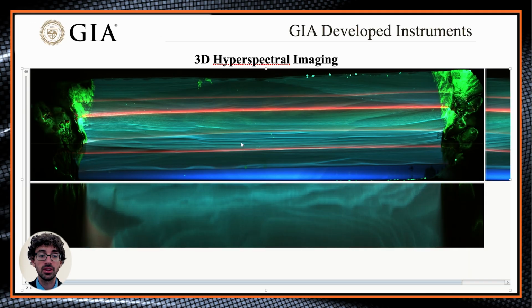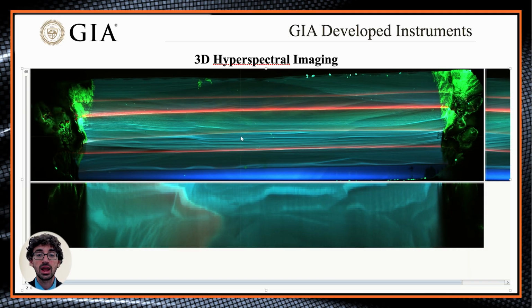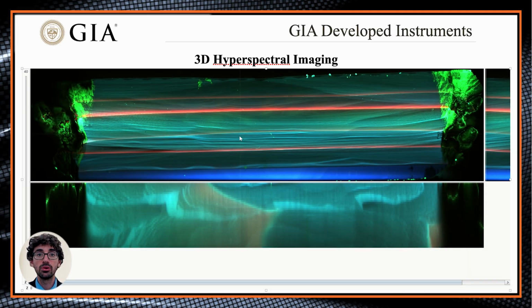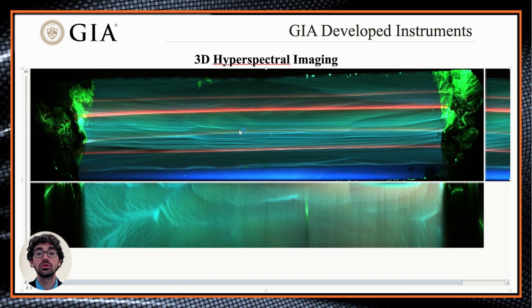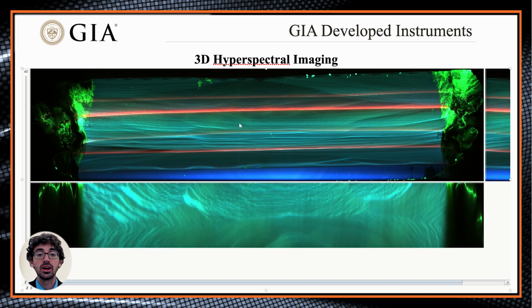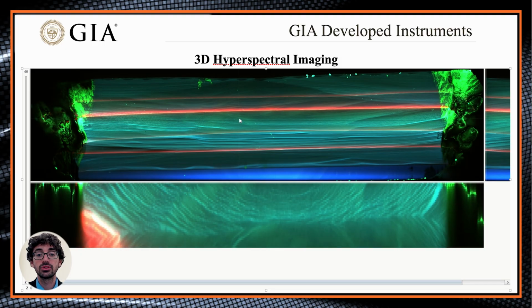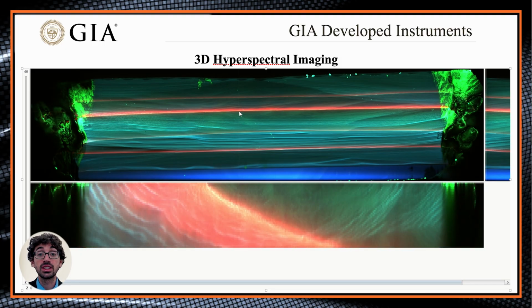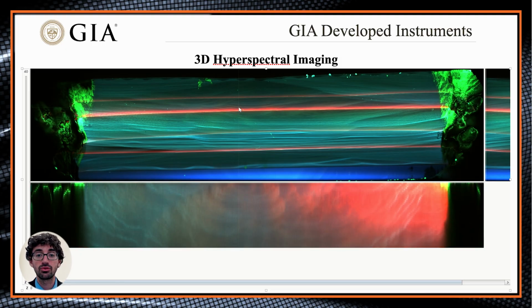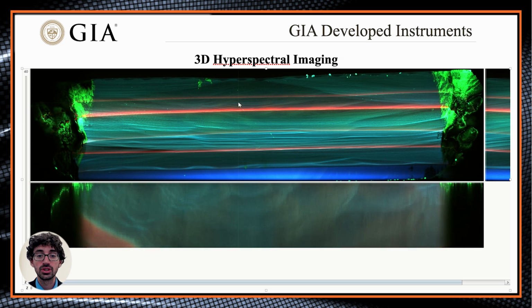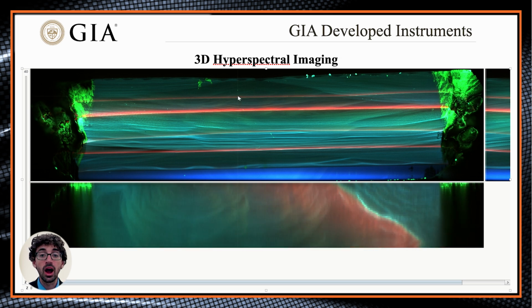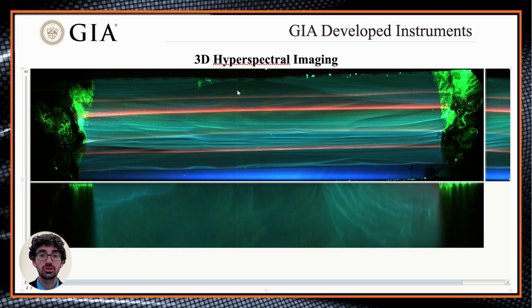The following video shows how this diamond evolved in the reactor, the step flow growth that is caused in a CVD reactor, incorporating different concentrations of defects as this diamond grew with varying conditions. And we are seeing this growing up from the substrate into the reactor plasma itself.